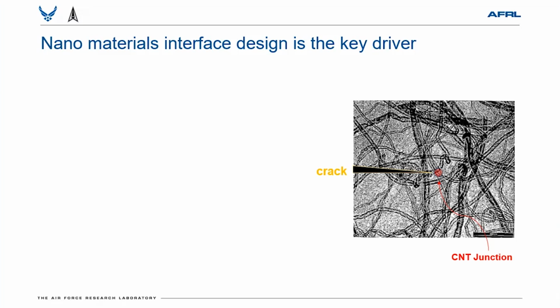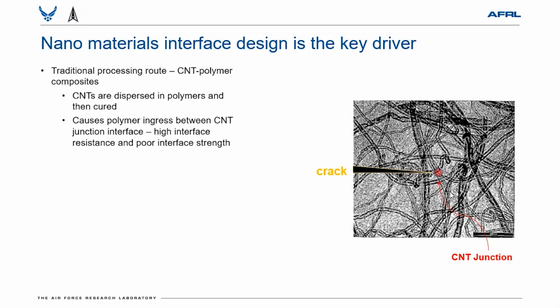Whereas if you can ensure these carbon nanotubes are interconnected with welded junction, if you will, for example, then what will happen, say in case of this crack propagating, if they are not robustly connected in all the nanotube mesh, then this individual nanotube will try to deter crack propagation, but not necessarily all other nanotube will contribute unless their network is robustly interconnected with welded junction and so forth. That's the concept. So with this network concept, we can boost up the properties that we are missing in just mixing carbon nanotube.